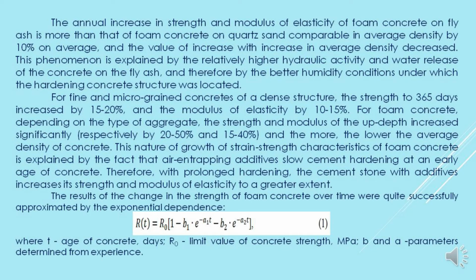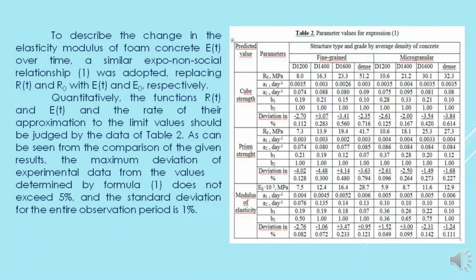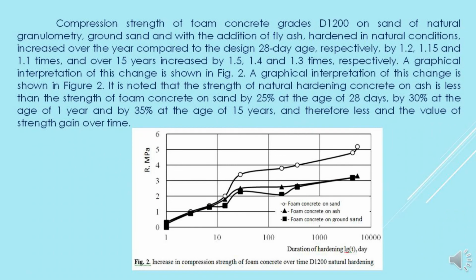The results of the change in the strength of foam concrete over time were quite successfully approximated by the exponential dependence 1. Quantitatively, the functions R(t), E(t), and the rate of their approximation to the limit values should be judged by the data of Table 2. Compression strength of foam concrete grades D1200 on sand of natural granulometry, ground sand and with the addition of fly ash, hardened in natural conditions, increased over the year, compared to the design 28-day age, respectively, by 1.2, 1.15 and 1.1 times, and over 15 years by 1.5, 1.4 and 1.3 times, respectively.